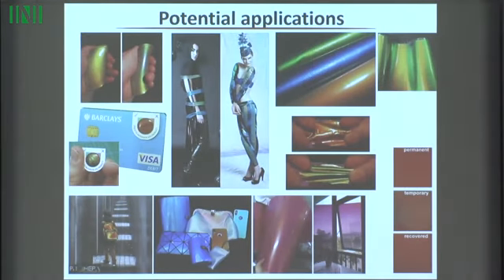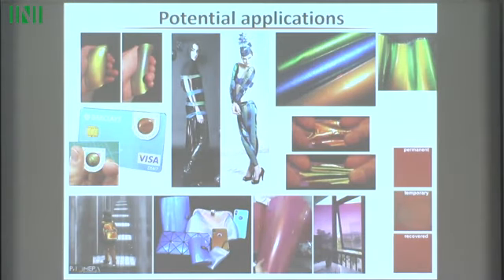The reason, so this is a sort of volume effect. Essentially, the light will penetrate many layers into the structure, so maybe 1,000 layers of these different spheres, and this complicated interference is what gives the color here. So that's nice, but if I wanted to change the color dynamically, say, then I have to change the entire volume. And that's quite a large volume. So if I want to make a low energy switching material, which we'll talk about later, then I'd really like something which effectively localizes the light more and affects it.